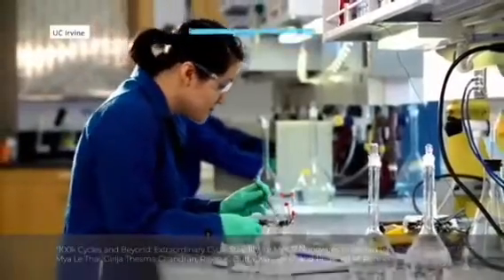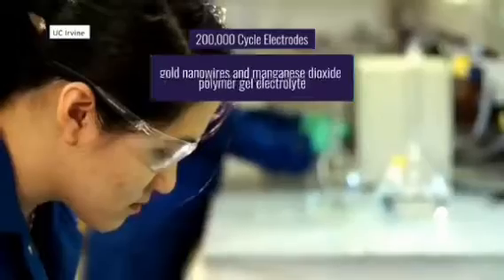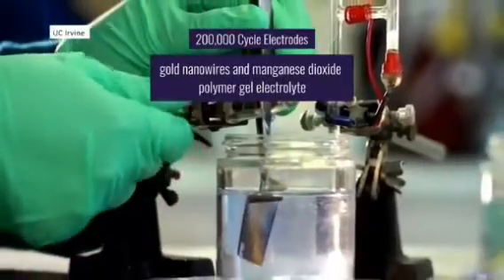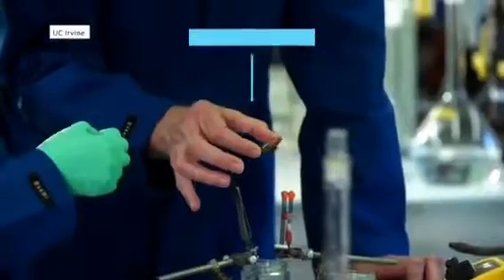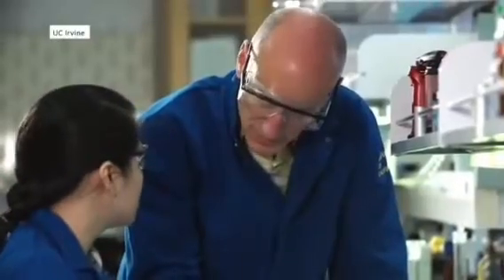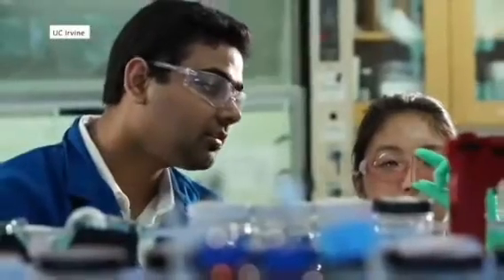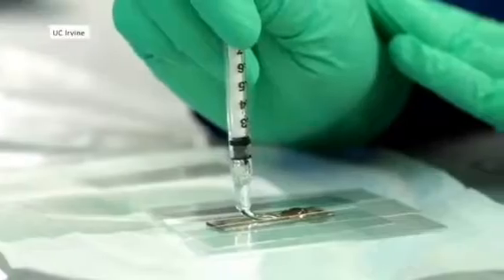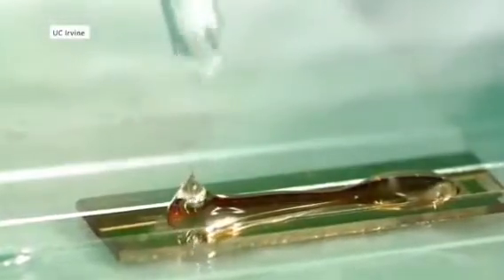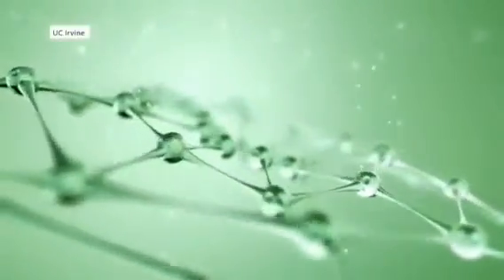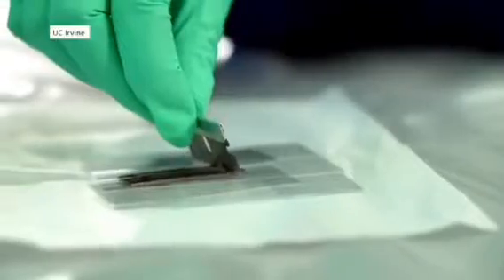Irvine have even produced electrodes good for 200,000 cycles using gold nanowires and manganese dioxide with a polymer gel electrolyte, and many other research efforts are ongoing with other diverse materials. One thing that seems to be sure though is that as soon as it's possible to mass produce suitable nanotechnology, we will be seeing it in our batteries in some form, and quite possibly in conjunction with silicon.